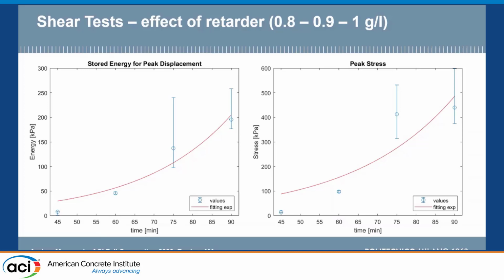There is a sudden increase of the strength with quite a high variability of the results. That is due to the fact that there is a very large increase of the strength in a very limited time window of only 15 minutes, which made it difficult to obtain the same repeatability of the results that we got at earlier times. And this is valid both for the stored energy and the peak stress.